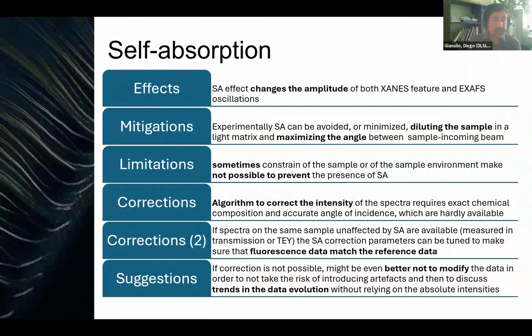A common procedure is to try and measure the sample, for example, with two different acquisition modes. Self-absorption is present more commonly in fluorescence. So if there is the possibility to also measure in transmission or in total electron yield, then the two spectra could be compared, and the correction parameters for the self-absorption could be, let's say, tuned so that the two spectra match. The spectra collected with the two different acquisition modes match each other.